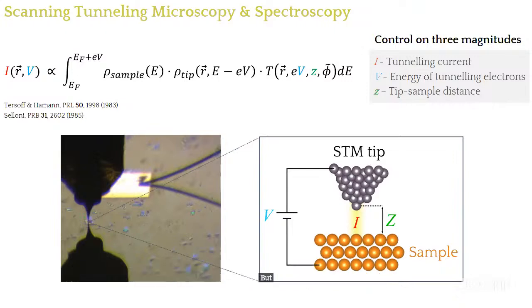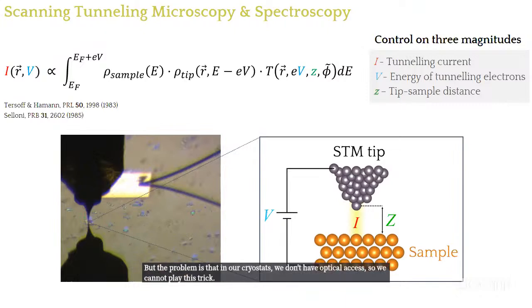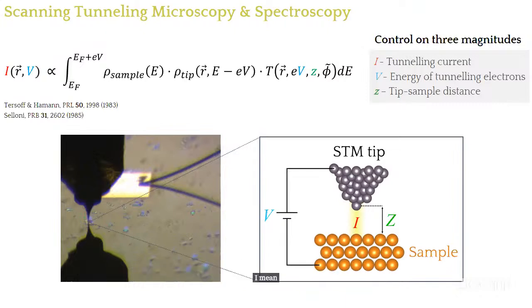But you can take any piece that you land on. But in the one that you have been doing with this moiré pattern, this is a single one, right? Oh, no, of course. Our device will be on top of this. Exactly. So this is the boron nitride flake, but our sample is even smaller than that. But if you are able to put your tip on top of the boron nitride, you're so close. But the problem is that in our cryostats, we don't have optical access, so we cannot play this trick. This is okay if you measure at 4 Kelvin, but otherwise it's not.